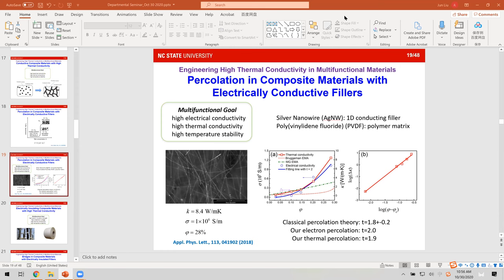But instead, thermal percolation is not easily observed, and there's still a lot of debate on that. So to form a thermal percolation, you probably have a larger percolation threshold and more requirements to form a percolation thermally, because that's also the difference, like I mentioned: you have electrical insulator and conductor, but you don't have an absolute thermal insulator. So even though you can have very low thermal conductivity in a polymer matrix, they're still not insulators, they still conduct heat, right? But electrically, if they're insulating, then it's insulating. So it's very hard to actually achieve absolute insulating and conducting.